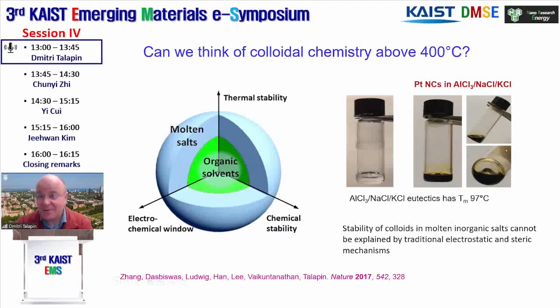And these are first examples, in that case platinum nanoparticles that have been dispersed in the eutectic mixture of aluminum chloride, sodium chloride, potassium chloride. And actually, this eutectic has a melting point of 97 degrees Celsius. So we're not talking about some outrageously high temperatures to work with. So you can do clever chemistries there and phase transfers and so on. And we've been lucky to identify that nanoparticles can relatively easily form colloidal dispersions in these molten salts.